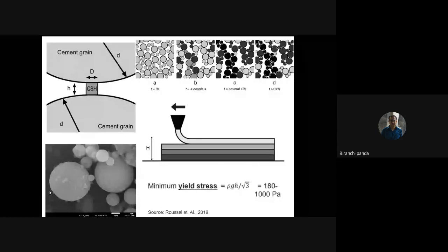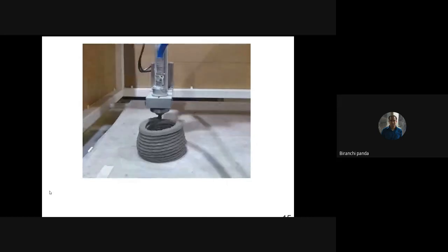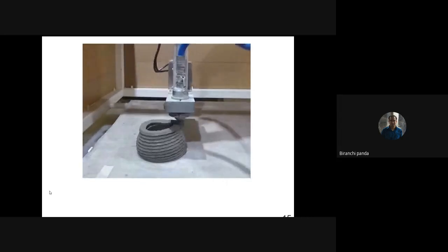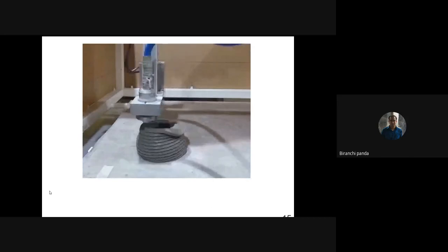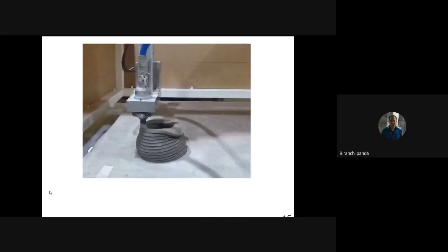But as I said, whenever we saw this fly ash under the microscope, we could see that they are like spherical balls. So what is going to happen when you want to replace cement with fly ash? Because these are ball-like spherical particles, they have a high tendency to roll over. They can easily flow away. So ultimately, when you replace cement with this waste material called fly ash, which has spherical particles, they can easily flow away. After deposition of 3-4 layers, the whole structure is going to collapse. As you can see in this video, because of the high flowability or low viscosity, this structure is going to collapse. Even when we tried other structures, after printing a few layers, the whole structure collapsed.